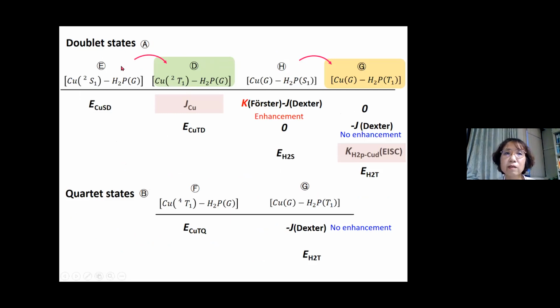Actually, if we have a doublet precursor, the direct matrix element between the triplet doublet state and the free base triplet state is just exchange interaction, which unfortunately is the same matrix element as with the zinc porphyrin, and this causes no enhancement. However, the triplet doublet state can be mixed with the singlet doublet state, and this triplet state can mix with an excited singlet state, and this excited singlet and the singlet state have a matrix element which causes the Förster mechanism.